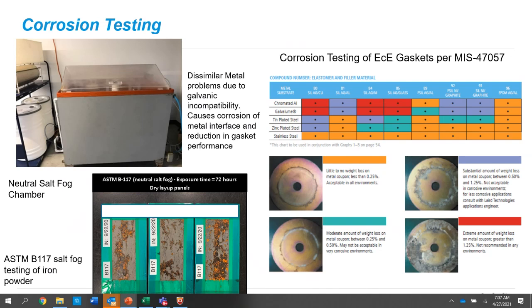We take that one step further. We've offered a new product starting last year. It's called ECE 130 and 131, which are passivated silver aluminum. So now we put a passivated coating on, which continues to help that. If you look at the bottom, you can see stainless steel. That's certainly a good choice if you can use it, because that's pretty much compatible with anything.